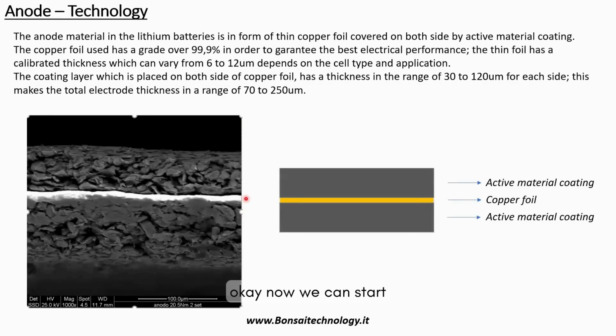Okay, now we can start to talk about the anode. The anode, as you can see on the left side of the screen, is a sandwich of thinner copper foil in the middle and then a graphite coating on both sides of the copper foil. In terms of thickness, the copper foil used is thinner than the aluminum used for the cathode. Usually the thickness right now move from 6 to 12 microns. Okay, so very, very thin.